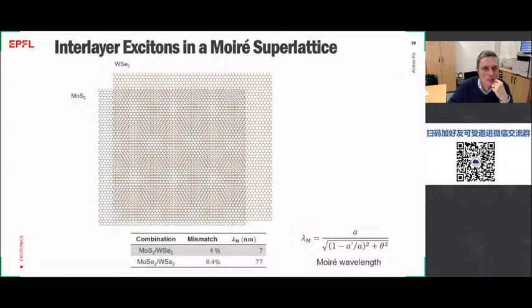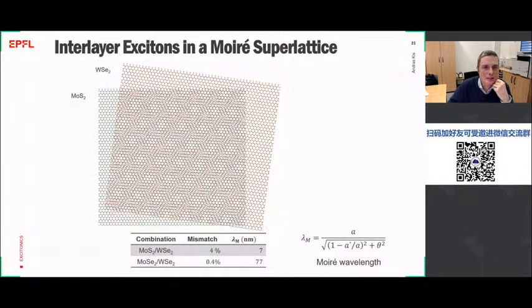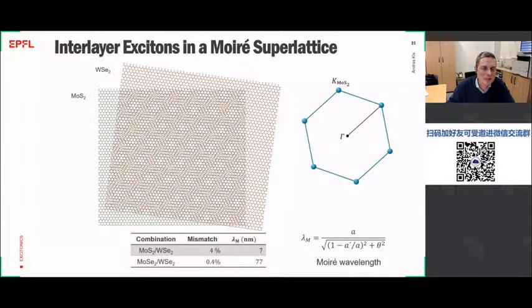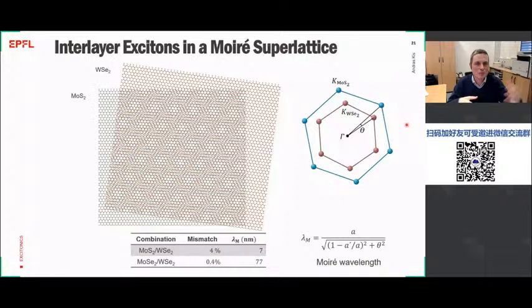In addition to just the lattice mismatch, you can also have slight rotation. And the resulting Moire superlattice can dramatically influence the properties of the excitons and also how much they can move around in this heterostructure. So the first thing that they influence about the energetics of the excitons is that, because we can have different lattices and also different relative orientations, if we take these two semiconductors on top of each other, then the transition between the electron in one layer and the hole in the other layer will involve points in the Brillouin zone which are no longer in the same position in K space. So they will not be spatially direct because the charge carriers are in different layers, but they will also be momentum indirect